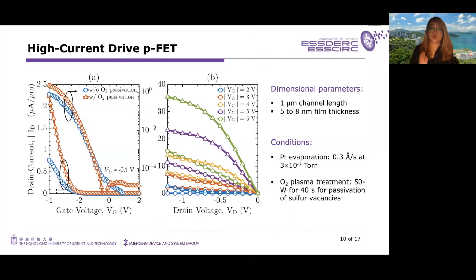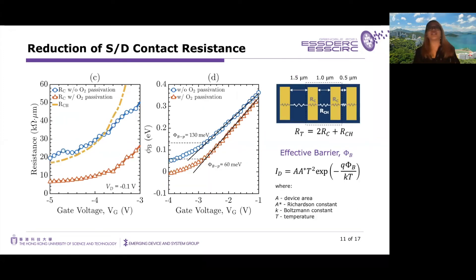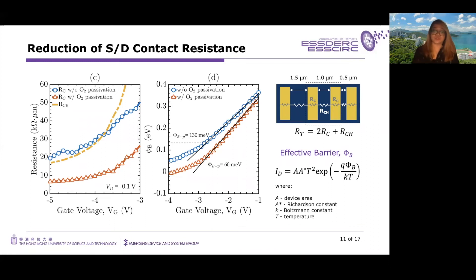Examining the effect of O2 plasma treatment in the PFET test structures, it is evident that the current drive improves by introducing a 50-watt O2 plasma for 40 seconds. We also characterized the contact resistance using the transfer length method. As shown conceptually in the top right figure, because of the O2 passivation, we can clearly observe a reduction in the contact resistance — noting that the contact resistance is also a function of gate voltage due to the global back gate configuration, where there is an overlap between the gate and the source-drain electrodes. The enhanced current drive is also explained by the improved carrier injection at the source–2D channel junction due to the reduction in the Schottky barrier height for holes.